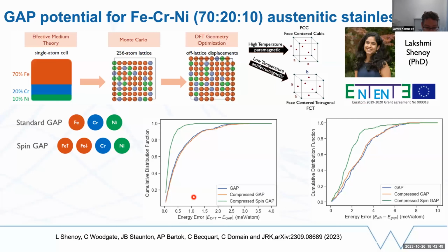So you can see here we've got significant errors of up to a couple of meV per atom on 5 or 10% of configurations, both with the GAP and when we do this species compression, which makes it faster but doesn't significantly reduce the accuracy. However, when we move from these 2 to the green, we introduce this additional species that represents the different spins. We get a really big improvement in the accuracy. Same thing for the training configurations and for the test configurations over here on the right. But more importantly, we start to correctly describe this tetragonal distortion. So let me go through that.